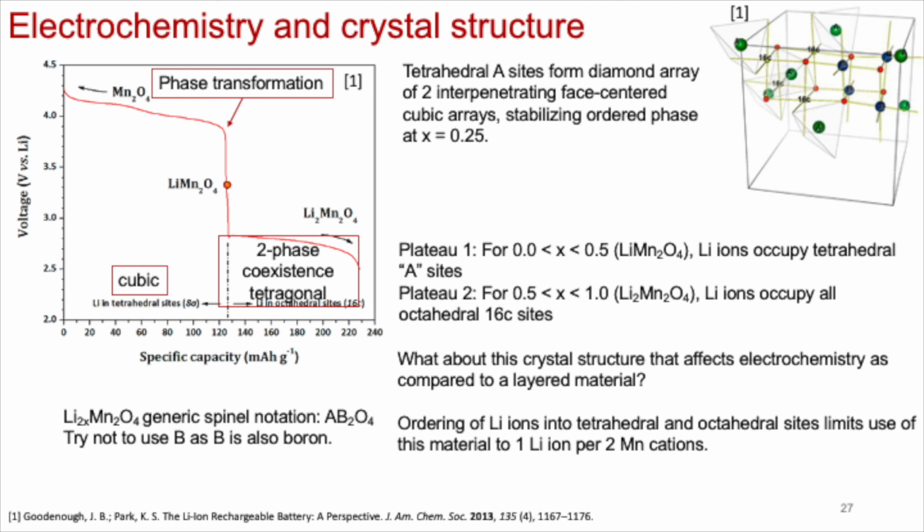So in terms of engineering, the fact that there's this phase transformation all based on the crystal structure, the manganese surrounded by oxygen, right? In this symmetry, the cubic going to tetragonal is the reason why lithium manganese oxide is not stable unless you limit your operating window versus the voltage or capacity. I mean, they're both related, right? So you can just cycle between here and let's say maybe here, and that's fine. You get this amount of capacity out and that's fine, but that's your limitation. It goes back to the crystal structure.